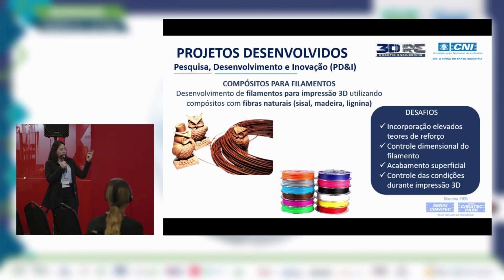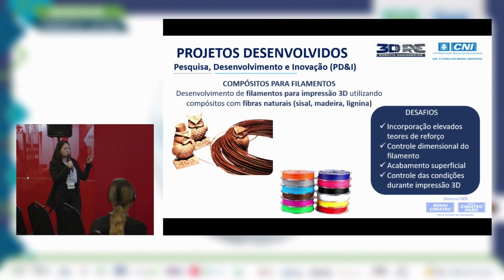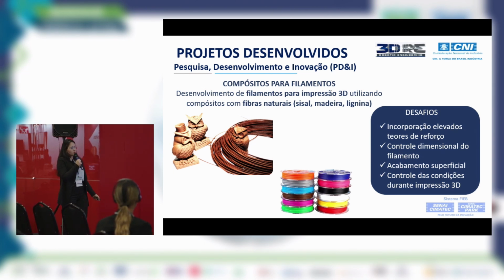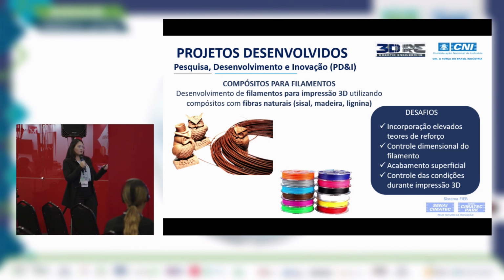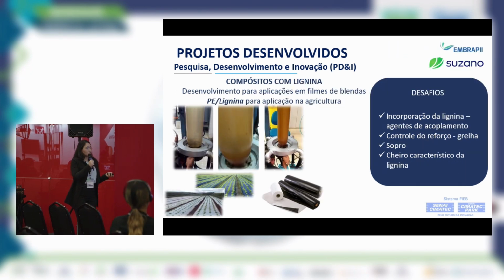Incorporating high amounts of fillers without changing the characteristics of the filament, because we need a filament with the same level of quality. We strictly control the size for 3D printing. That's the second challenge, right? The size control of the filament. So we need even production throughout the process. Superficial finish can interfere with the piece that is going to be obtained later with the use of the filament, and the control of the conditions during the 3D printing. Depending on the polymer, we need to control the temperature during the 3D printing so that we obtain the proper pieces by using these composites.